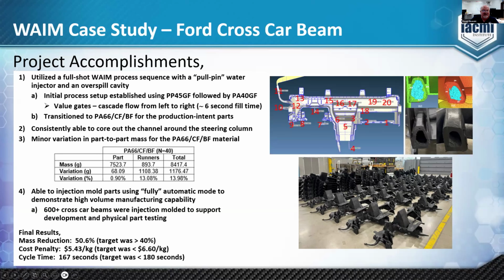Approximate fill time was 6 seconds. We were consistently able to hollow out the channel around the steering column, and we saw good part-to-part mass variation with the production intent material, which was a combination of carbon fiber and basalt glass fiber. In that case, the part came in with a variation of 0.9%. Typically you like to see that below 1% for an injection molded part.